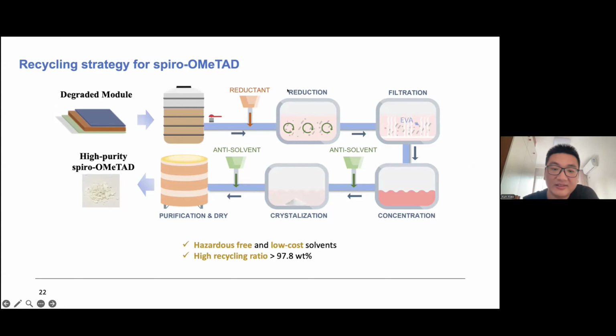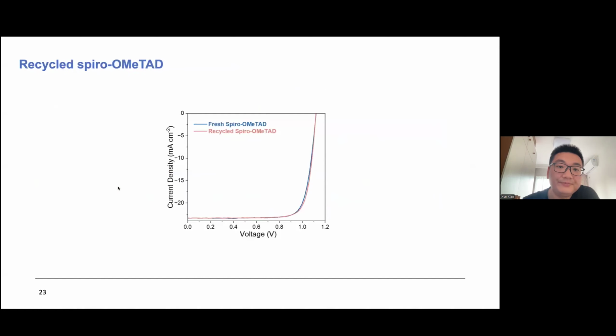So with this process, we use hazard-free and low-cost solvents to achieve a high recycling ratio, more than 97 weight percent of the spiro-OMeTAD. And also the spiro-OMeTAD that we recycled is neutral, it's not doped. We tested the recycled spiro-OMeTAD compared with the fresh spiro-OMeTAD, and the device efficiency is almost the same.